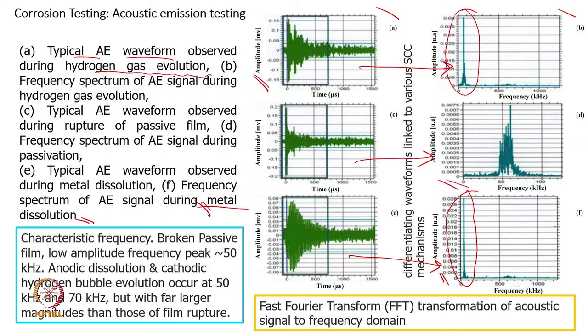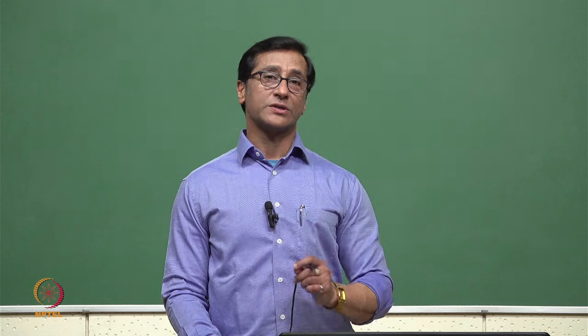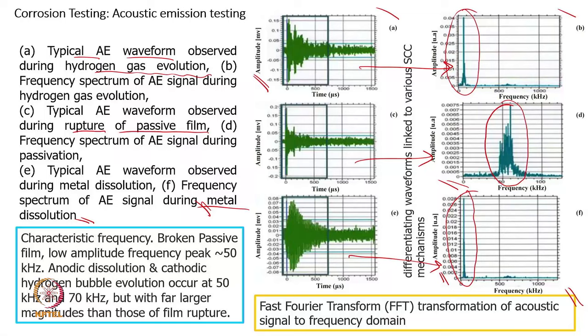The second one, the B one, is where we say there is a rupture of the passive film. A rupture of the passive film is also possible, and that signal comes. Now this kind of R&D is very important. Of course, it is beyond the scope of our present course, but this is possible by fine tuning, and I think particularly the physics field is really required for this kind of response analysis. That's what we are showing clearly here: passive film breakage comes roughly at 50 kilohertz, anodic dissolution or cathodic occurs around 50 to 70, and these responses are almost similar.